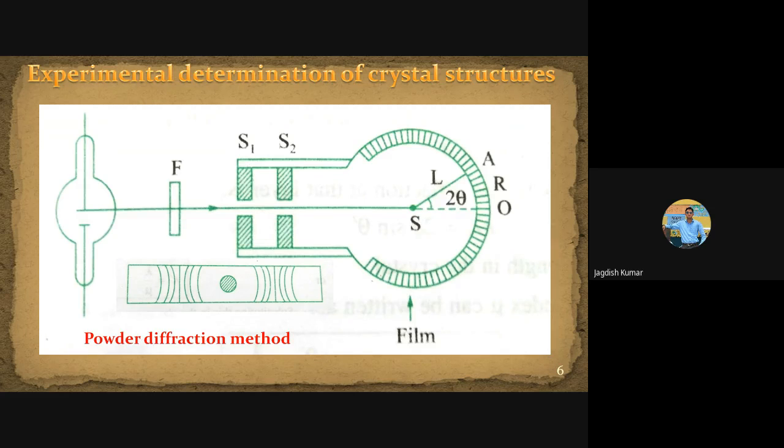Usually whenever I'm synthesizing a sample and then doing some sort of doping, we have a big database from which we can guess where we are getting the peaks and what is the possible crystal structure. From that we pick the space group, and then we also put in the atomic positions in the software, and those are all tentative. We decide some tentative lattice parameters, then some tentative atomic positions. But of course, we know the stoichiometric ratio or the formula of the crystal we have synthesized.